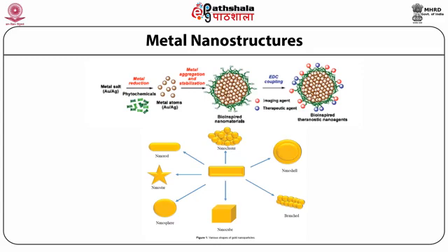Now it's interesting, there are a lot of things known about these metal nanoparticles, and if you change the ligand on the metal nanoparticle, they can be used as therapeutics or sensing. Many of these metal nanostructures like gold nanoparticle or nanorod or silver nanoparticle have a unique property called surface plasmon resonance. This is a unique optical property demonstrated by the pool of electrons in the metal. If you have a spherical nanoparticle, you get one very characteristic surface plasmon band. But if you have a rod-like structure, those electrons can oscillate in 2 different directions, longitudinal or transverse, and based on that there are two different types of band in surface plasmon resonance. This is what you can see on the right hand structure.